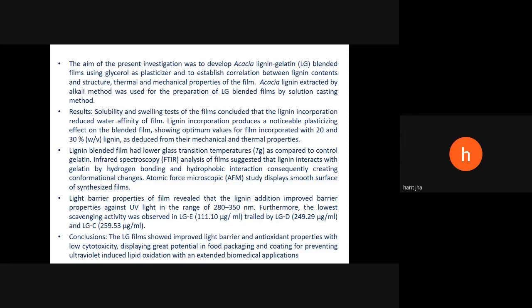In results, we found that solubility and swelling tests of the lignin films concluded that the lignin incorporation reduced water affinity of the film. It is important for food packaging application because you need relatively hydrophobic films and hydrophobic packaging material. Lignin incorporation produces a noticeable plasticizing effect on the blended film, showing optimum value for film incorporated with 20 and 30% lignin as deduced from their mechanical and thermal property.